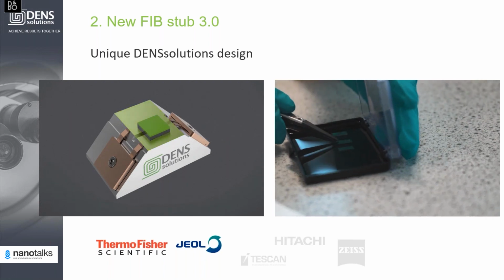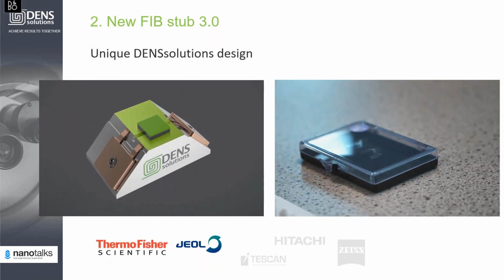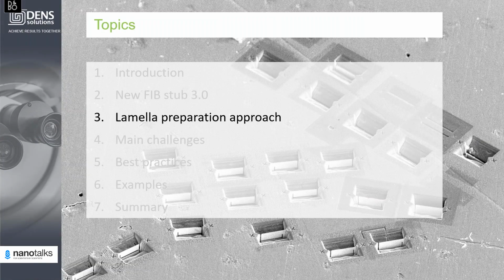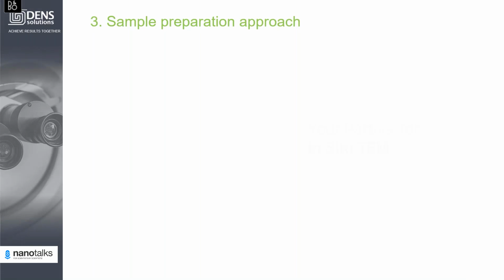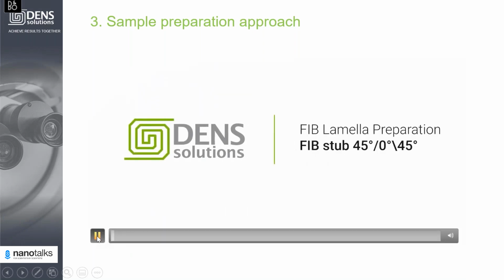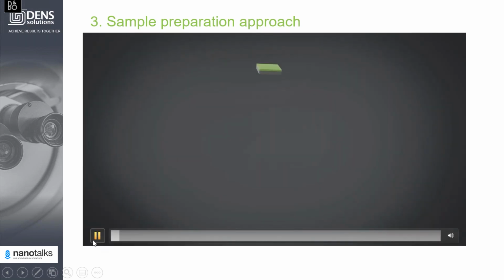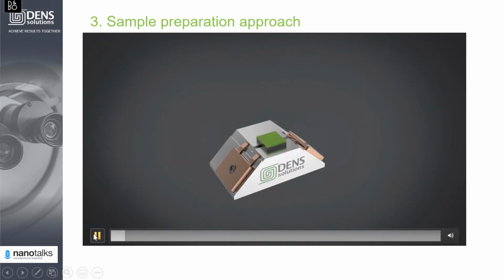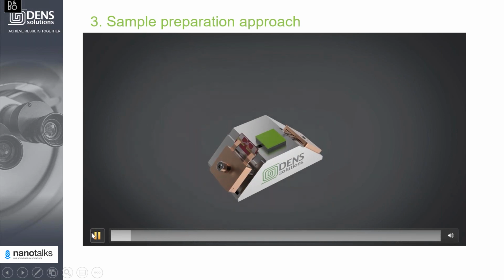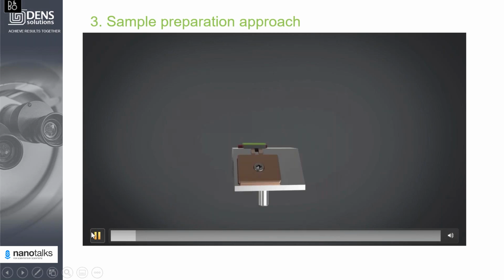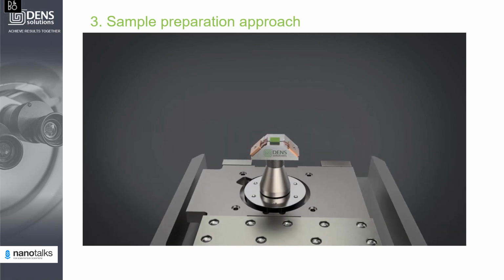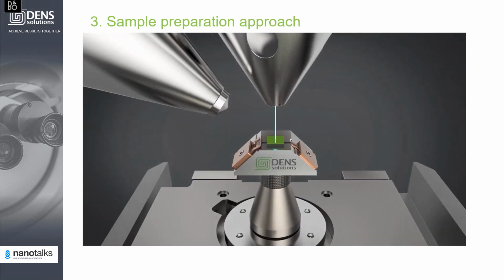As I mentioned, the process is very simple to load and unload the nanochip. And secondly, you don't need to use any more carbon sticky tape to fix the chip, which makes the process cleaner. So how do we do the sample preparation using the FIB stub? In the following animation, I'm going to explain in detail the whole process. We put the sample on the FIB stub, we put the nanochip, we vent the chamber of the FIB, put it inside, and pump it.